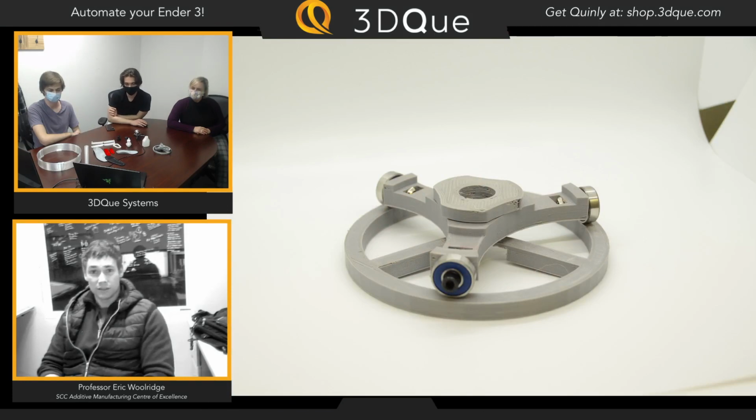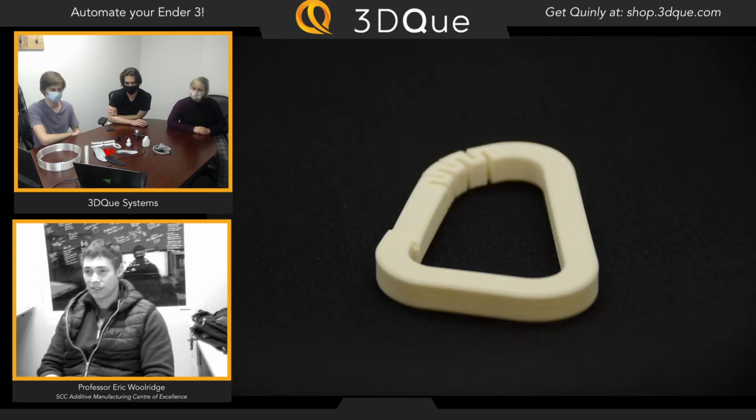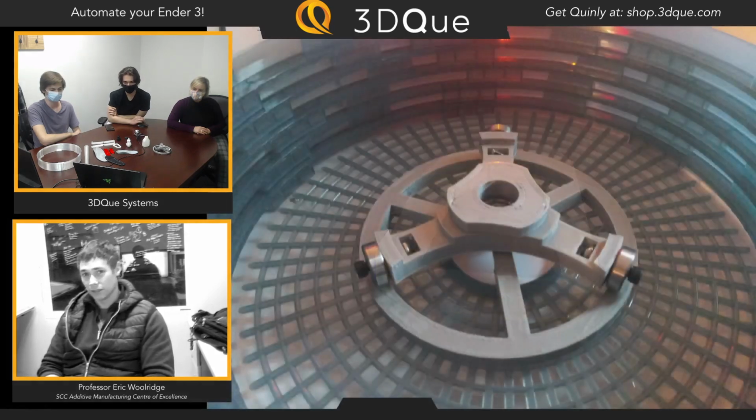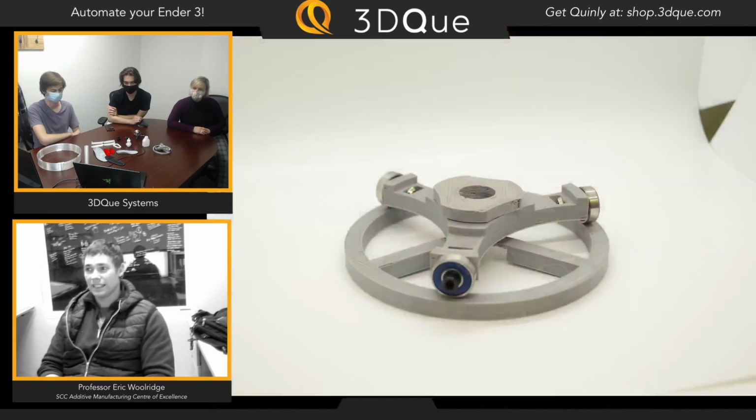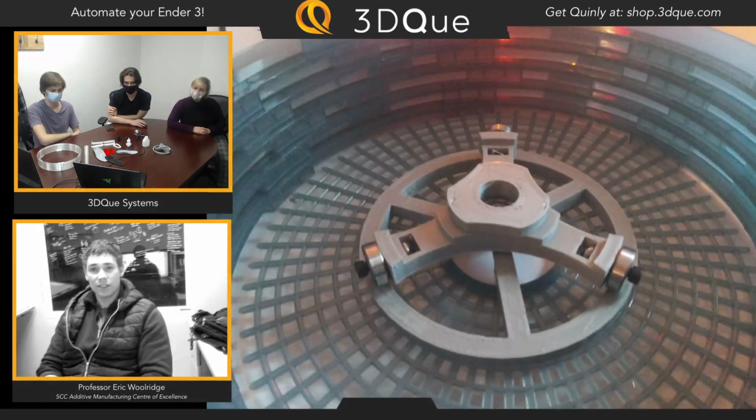PETG is great. We printed a tremendous amount of the face shields out of the PETG side of things. It's stronger. It has the heat resistance the PLA doesn't have. It typically has just a little bit more flexibility. It can have a really nice look to it if you really compress those layers. So adding in a stiffening agent, like a carbon fiber component, to increase resistance, or maybe even make it more of a hard material, maybe increase its tensile strength just a little bit, it just gives it that extra bump. And I think you'll see a lot more of that.